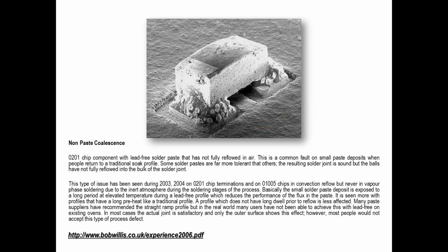What we've seen over the last couple of years is where we're looking at ultra small deposits, like on very, very small CSP type packages or 01005 or the next generation of packages, we've seen this again. So with vapor phase, you don't get it. In air reflow, you can get it. In air reflow, but with nitrogen, it's less likely. So again, you've got to look at the capability of your solder paste material for your process, but also the smallest deposit you can actually get away with successful reflow without this particular phenomena.